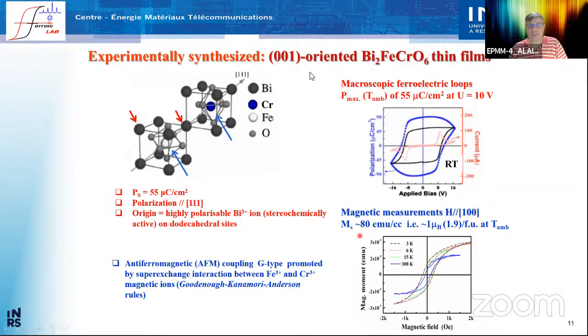So this is actually the experimental part. Okay, so we have here the structure, which is a double perovskite, with this unit not the same as this unit. So the unit cell is composed of 2 cubes, and you have here the ferroelectric loop and the ferromagnetic loop. You see that in the thin film form, the ferroelectric loop is a little bit leaky. At low temperature, it's much better, and the magnetic properties are actually pretty good. They are indeed almost 1.9 Bohr magneton per formula unit at room temperature, which is almost the 2 μB per formula unit predicted theoretically. So we were very, very happy about that.